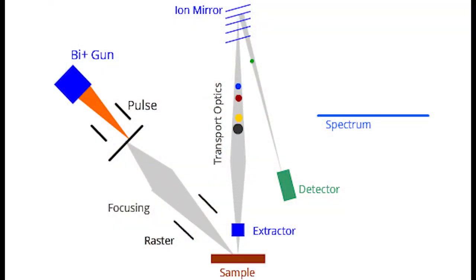Hello, this is Angel, and I'm the lab manager at Analytical Instrumentation Facility at NC State. ToF-SIMS is a highly sensitive surface analytical technique, typically using a pulsed and focused ion beam to produce secondary ions from outer 1 to 2 nanometer of the materials. The ejected ions are then extracted and measured by their flight time, which is proportional to their mass-to-charge ratio.